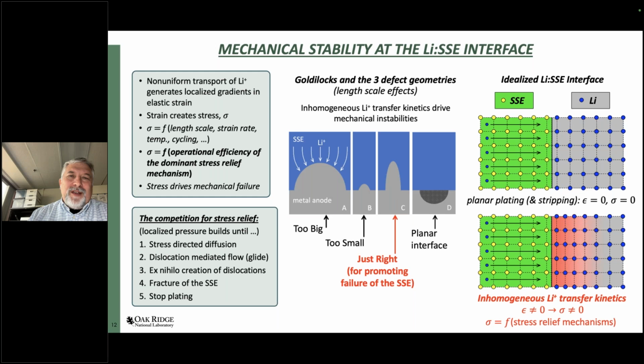Now, big morphological defects like this one pose less of a threat because the stressed volume is big enough to have a high probability of finding the mobile dislocations or the active sources that are required to keep the pressure low, close to that half MPa number. At the other end of the spectrum, small defects like this one also pose less of a threat, because the defect is small enough that diffusional flow can act as an efficient stress relief mechanism. So it's the morphological defects between these two limiting cases that are going to be the potential problems.